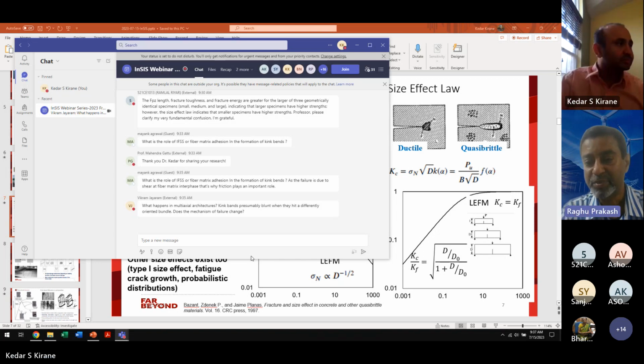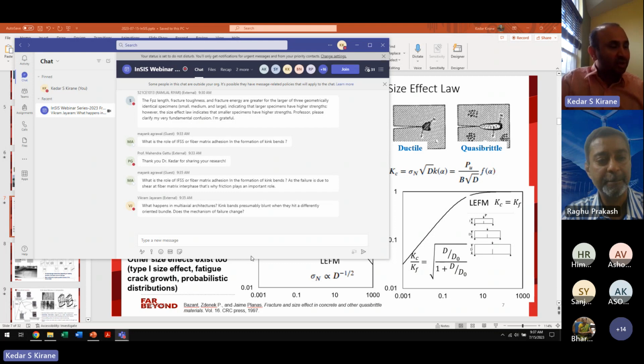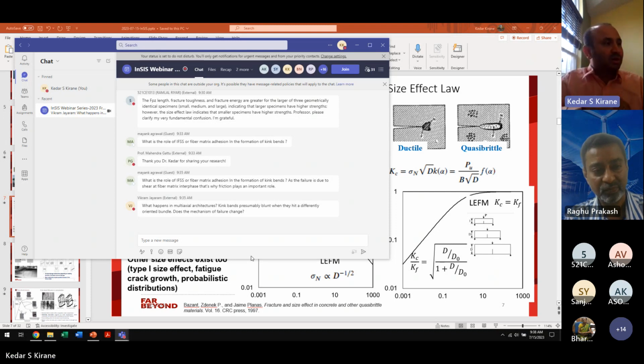This question is from Vikram: what happens in multiaxial architectures? Kink bands presumably blunt when they hit a differently oriented bundle. Does the mechanism of failure change? That is also a great question. What we saw today was just a single layer or a laminate with all layers oriented in the same way. Now, if you imagine a laminate arrangement with layers oriented differently under compression, then probably the layer whose fibers are most aligned with the loading will experience the kink band, and the other layers will still remain intact and maybe blunt.